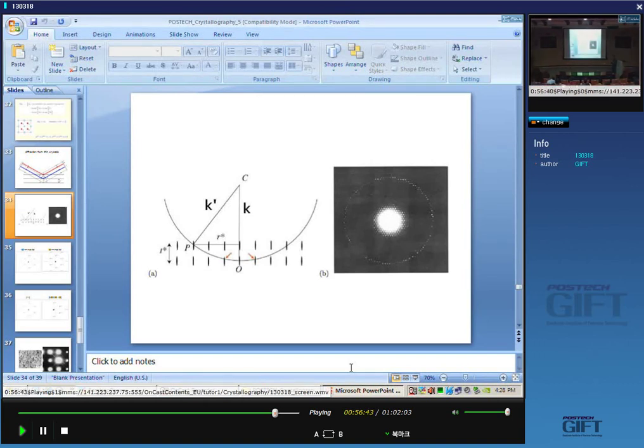Because you can think about each reciprocal lattice point as being extended normal to the plane of the foil. As the foil becomes thicker, this spike becomes narrower and becomes a point if your crystal is very thick. So even though the Bragg condition may not be exactly satisfied here, in other words, k dash minus k does not equal g, you will get diffraction. So in the electron microscope, it's very easy to get diffraction. Whereas when you do X-ray diffraction, you're looking at thicker crystals, and you have to set it up accurately in order to get diffraction. Otherwise, you use a powder or something like that so that you present many, many orientations to the X-ray beam.